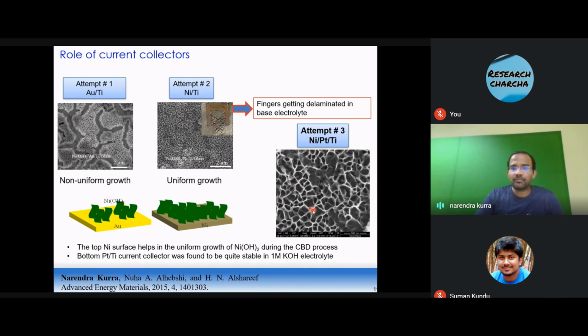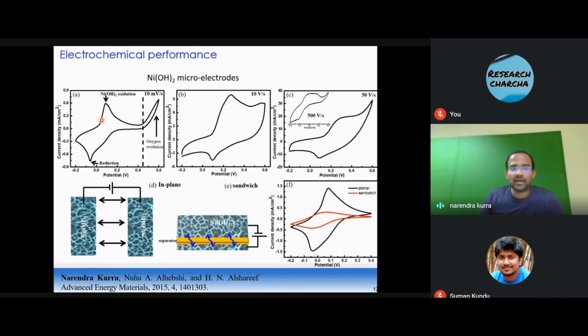So at this stage we were successful, and then we made nickel hydroxide microelectrodes, and we could test the electrochemical performance of nickel hydroxide microelectrodes. Indeed, these devices can be scanned despite the low electronic conductivity of nickel hydroxide. We were able to run up to 50 volts per second. Still, we see the preserving of redox peaks even at high scan rates.